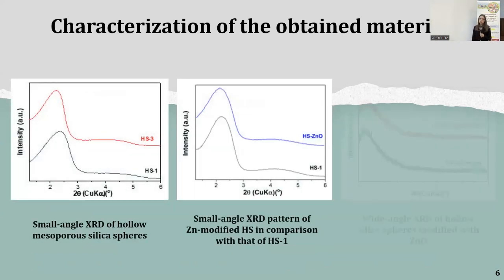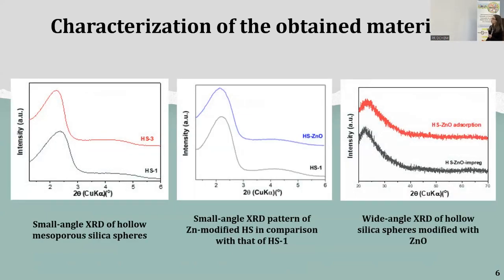The obtained materials were characterized by various methods. The small angle XRD pattern of hollow mesoporous silica spheres exhibits one intense peak attributed to 100 Bragg reflection, which is characteristic to MCM41 mesoporous silica, indicating the ordered mesoporous structure.